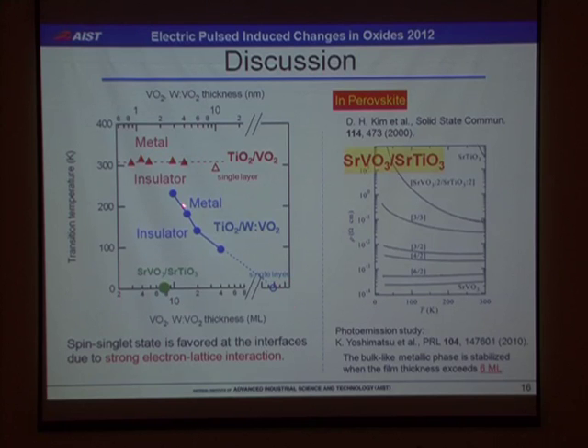And the effect of electron doping is weakened by reducing the film thickness, the VO2 layer thickness. A similar reduction of conductivity was seen in the perovskite structure, in this case strontium vanadate and strontium titanate superlattices. But the sensitivity to the film thickness is more significant in the rutile structure. This is due to the very strong electron-lattice interaction in this system.